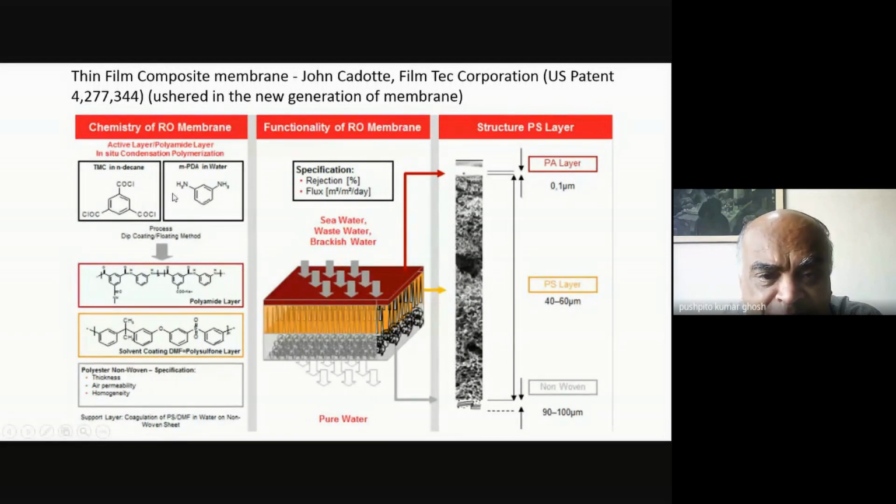online. And then what happens is that it is passed through a solution of an acid chloride in some non-polar solvent like decane or hexane. You take some solvent like that. So then the acid chloride will react with the amine, release HCl, and it will form in situ this polyamide layer. So this is your amide, C double bond O NH, and is basically a polymer of this.